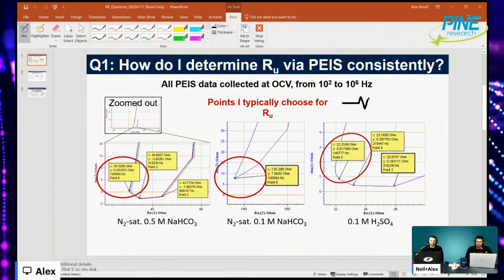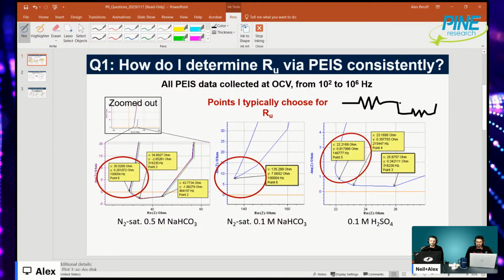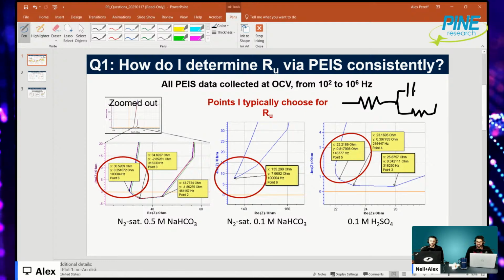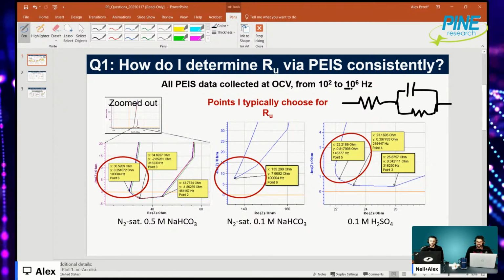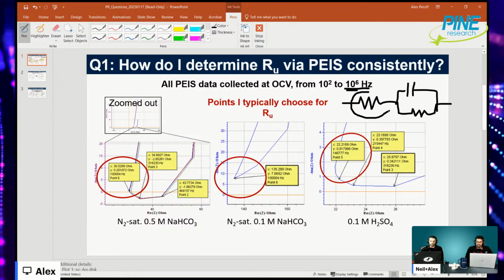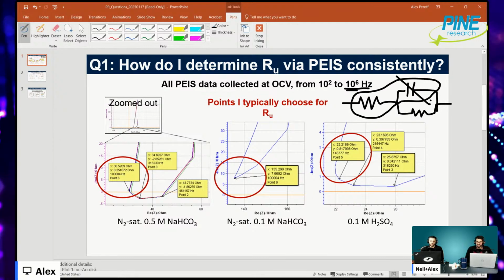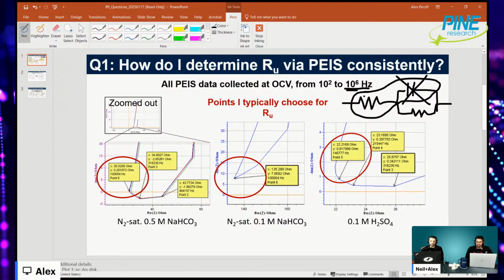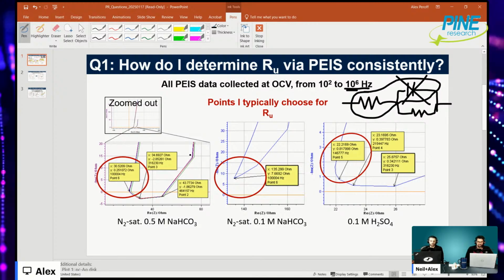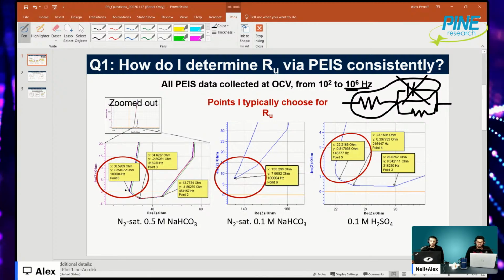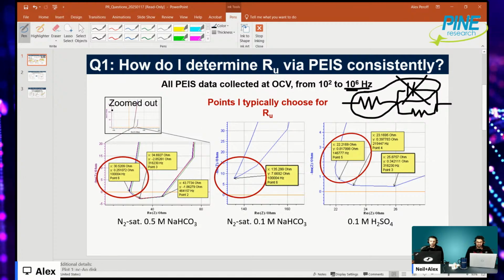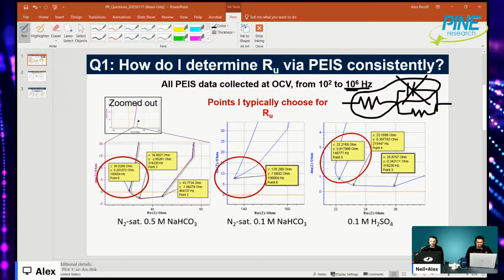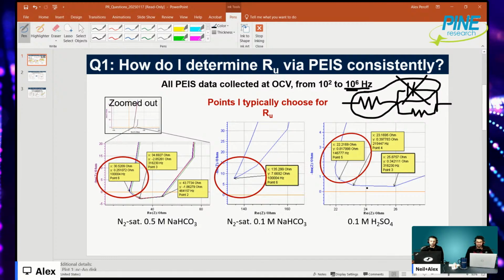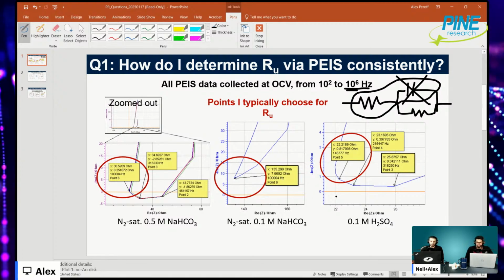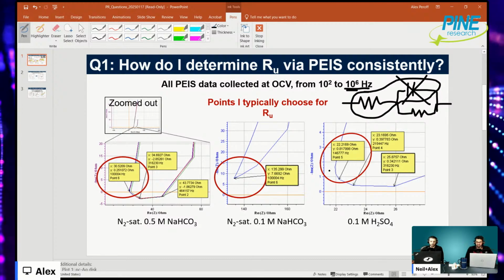Now this all kind of comes from how we model the electrode interface, and the fact that at high frequencies we're primarily looking at this region, and this guy is effectively equal to 0 when we're at very high frequencies. But when you actually do potentiostatic EIS, you get several data points in the high frequency region. So this is a zoomed out picture of the EIS, and you get these data points. It's not like it just shows up as one data point. This is your solution resistance. But which one of these data points do you actually use?